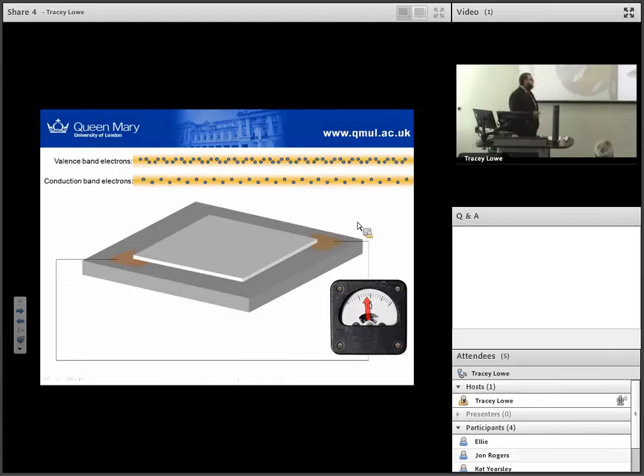And they work kind of like this: you've got your metal oxide in an oxygen atmosphere. Some of the oxygen will adsorb onto the surface. In a surprisingly thermodynamically stable reaction, you get some ionization to produce O2 minus and this kind of thing. Because we've taken some electrons out of our conduction band, for an N-type material anyway, we'll see that our resistance will change across our interdigitated electrodes. It will go up in this case.